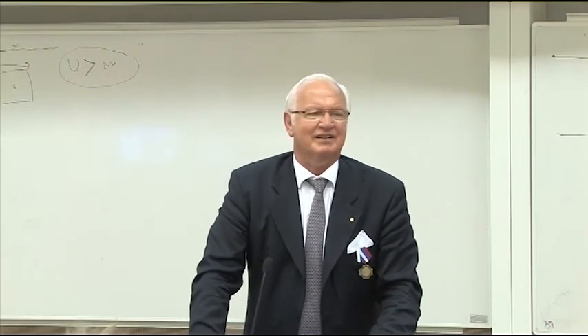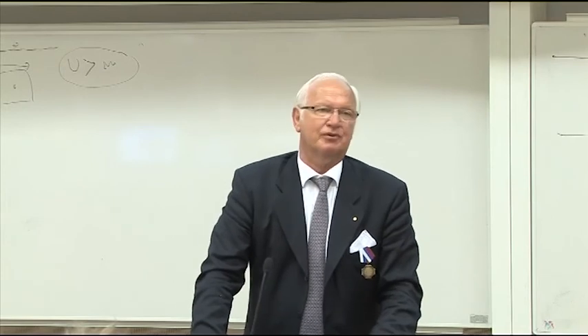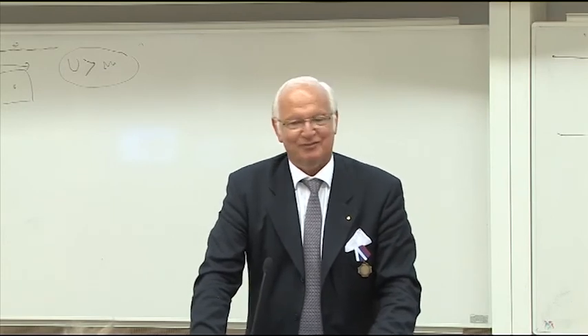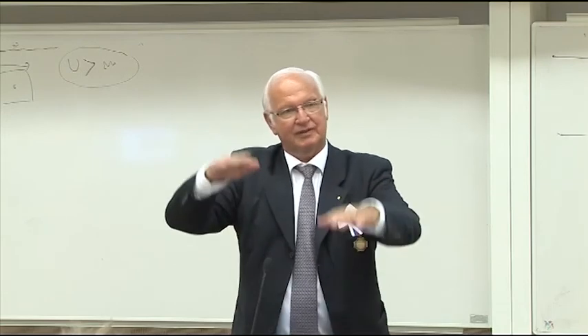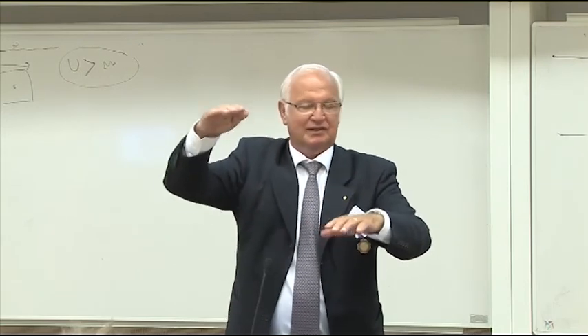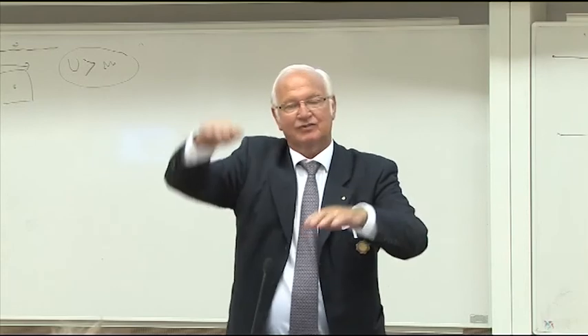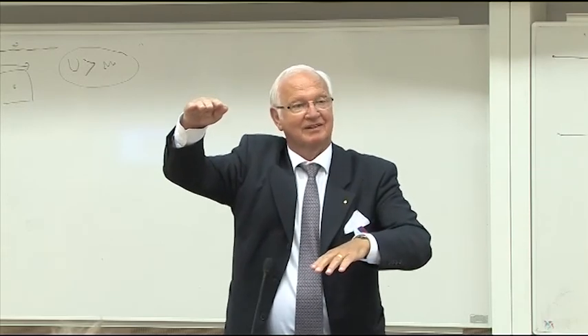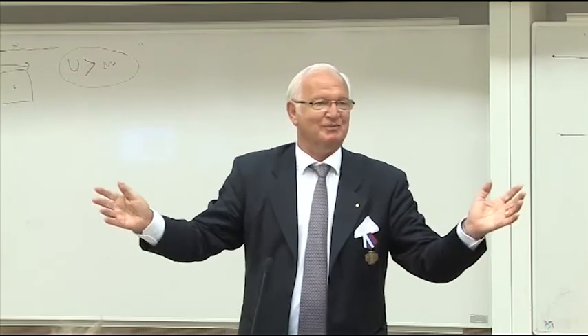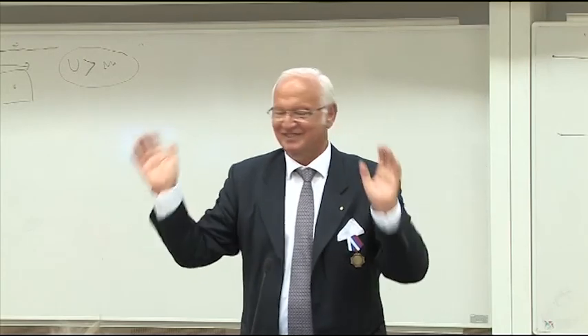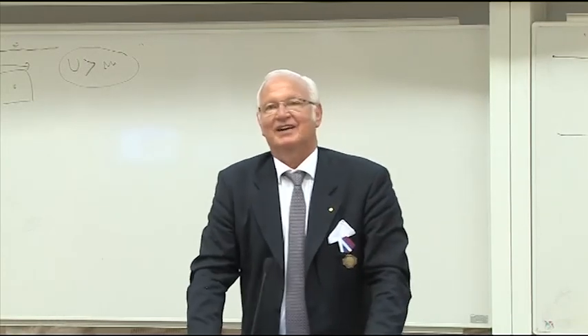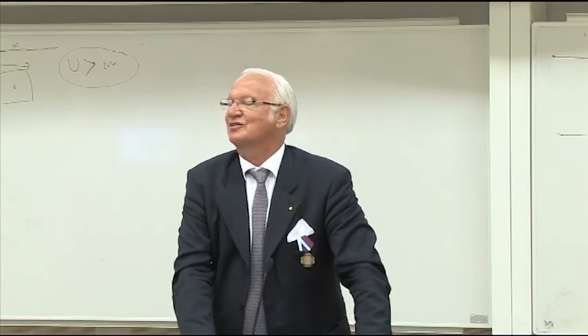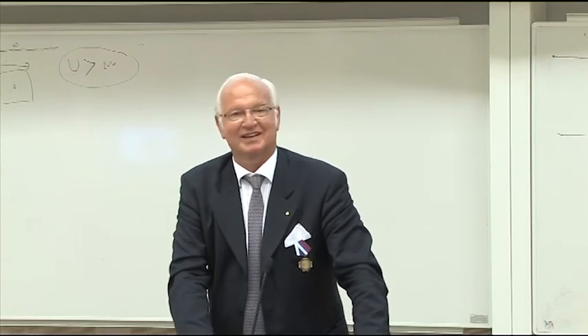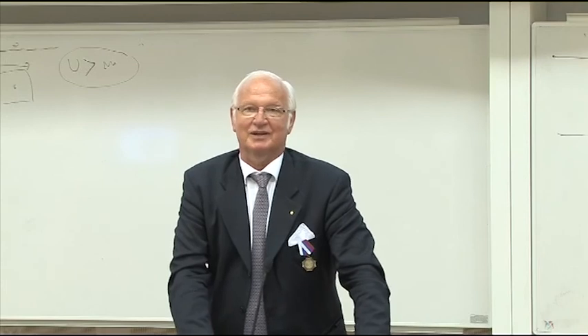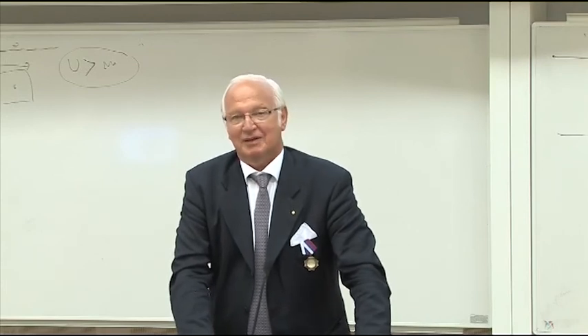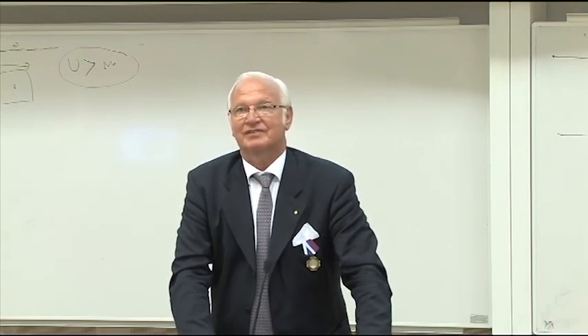But so I did the calculations, and I found the appropriate energies. And for God's sake, this energy difference between these two valence states should have been almost zero. It was 2 eV. So all my plans about writing a simple article disappeared immediately. So I had to start to think about what's wrong with everything, and that was actually why I came up with this work on cerium as such.